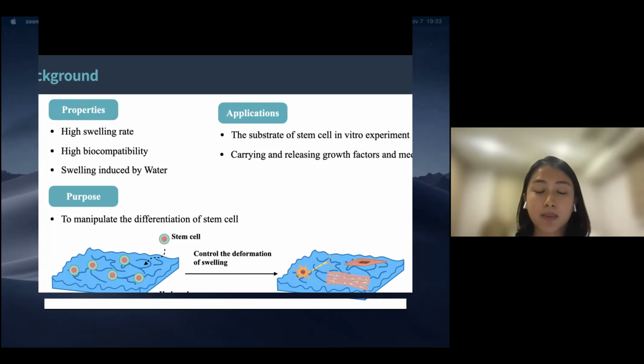And besides, by different production, it can carry and release growth factors and medicine to help the stem cell growth. So in our project, we use a special particle to cause wrinkles on the hydrogel surface, and the wrinkles will apply stress on the stem cells, which will be a mechanical stimulus to trigger the stem cells to differentiate into different functional cells. So today I will mainly focus on how to control the wrinkles of the hydrogel film by adding the special particles and building up the simulation models to find out the optimized design of the hydrogel film, which will be the best substrate for stem cell differentiation.